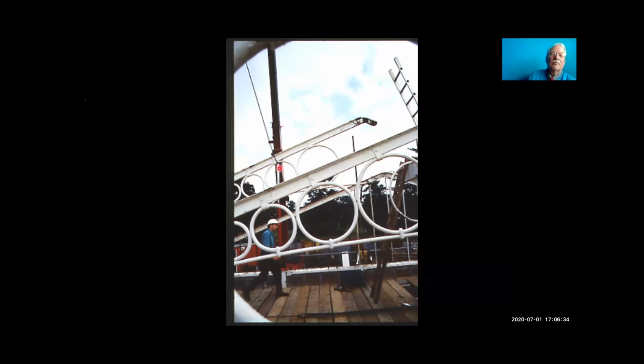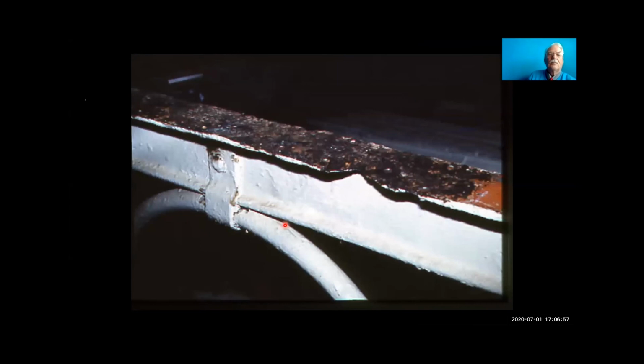So the whole operation must be controlled by what's called a banksman, a conservator who knows how to get these joints separated without doing damage. That's really important because you can destroy cast or wrought iron structure by leaving it to somebody who doesn't really know the metal, the capabilities of the metalwork. The problem here was that these bulbous T's had been repaired and the repair plate hadn't been sealed properly. So nothing wrong with this 100-year-old material here.